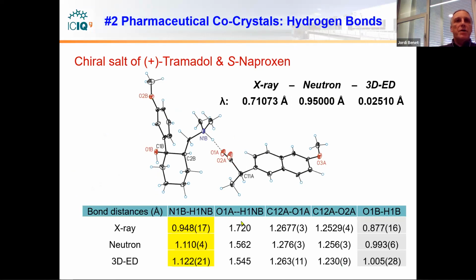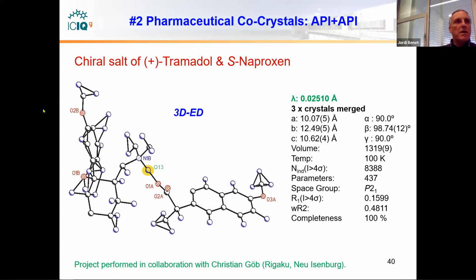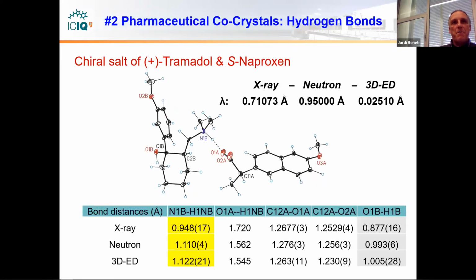By comparing the distances, for example, of this hydrogen bond, you could see, as expected, that with X-rays the distance was more shortened than expected. Using neutron radiation, this should be the correct distance of the hydrogen to the nitrogen atom. And finally, with 3D-ED, we got slightly more elongated distances, but quite close to the neutron diffraction experiments. Of course, we have a high standard deviation, and I need to work a bit more on the structures, but it was quite promising that you could localize directly most of the hydrogen atoms just from the remaining electron density.